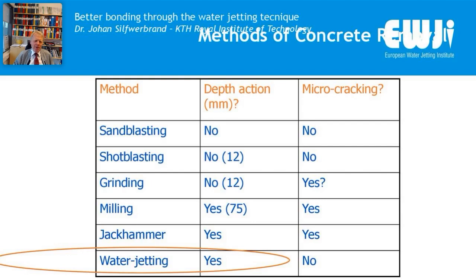Then you have grinding, and that could go somewhat deeper. We do not know exactly the amount of microcracking after grinding, but I guess that there could be some, and still it is not a method that has a large depth action. And then you have milling, and then you have jackhammers, and of course you can remove a lot of concrete with these two methods, but unfortunately they are introducing microcracking. And then finally we have the water jetting, or the water jet technique, and it has a depth action. You can remove several centimeters, and you can continue if you wish to remove more concrete, and the amount of microcracking is very, very small.